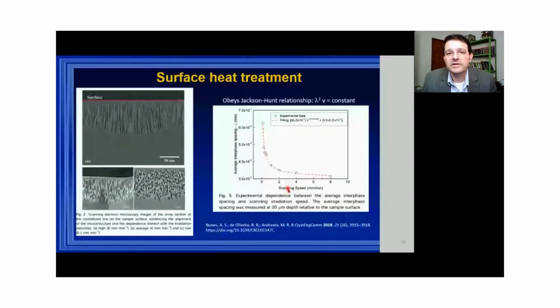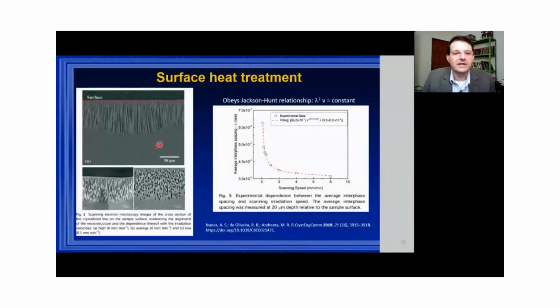Another example of heat treatment is that you can create lines of crystallized material. So you can make a vitroceramic on a glass, a localized vitroceramic. Here we have a glass whose composition is at a eutectic point on the phase diagram of calcium silicate and lithium silicate. And then you can see it when you have a very fast line passing through the surface of the glass.